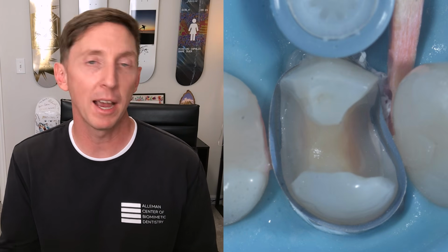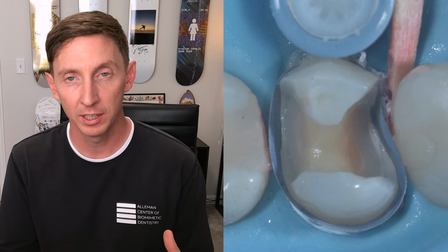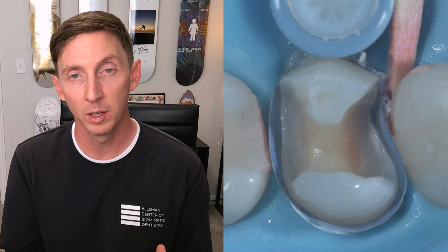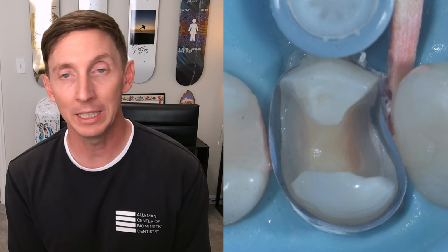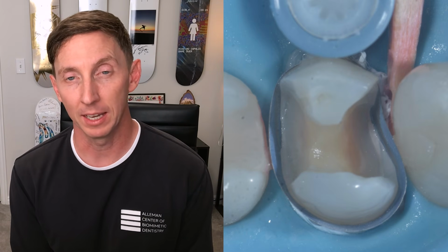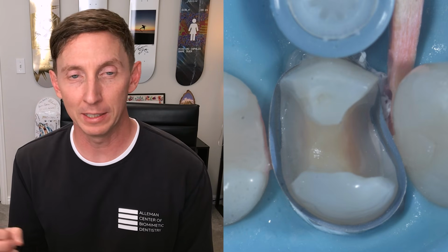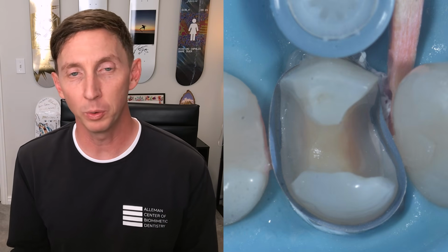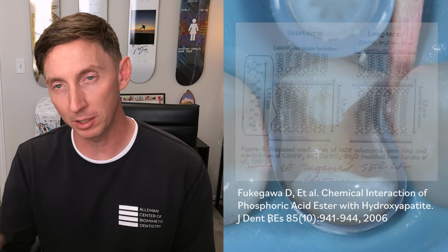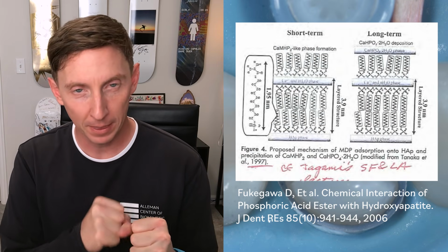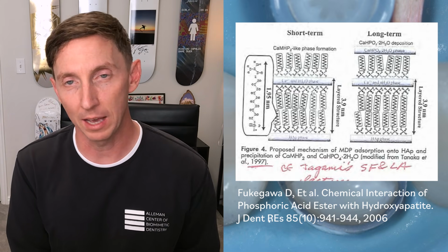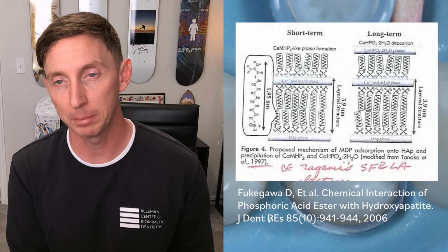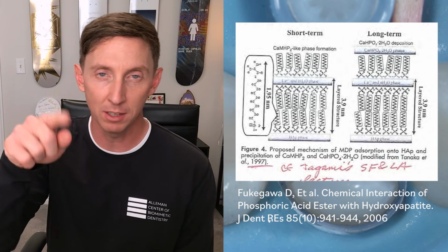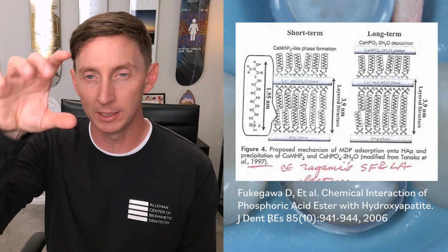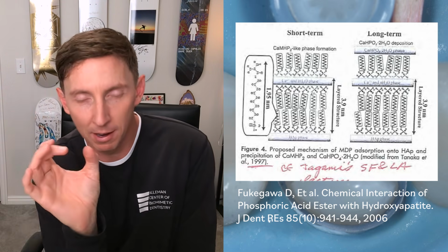So there's not just a micromechanical interaction that's creating a strong hybrid layer, but in this case, with a mild self-etch adhesive, we are seeing an ionic bond take place, where there's an electrostatic interaction between the phosphate end of the MDP molecule with the calcium found in hydroxyapatite. And so they kind of have these long carbon chains, and then the hydrophilic end is interacting with the dentin.